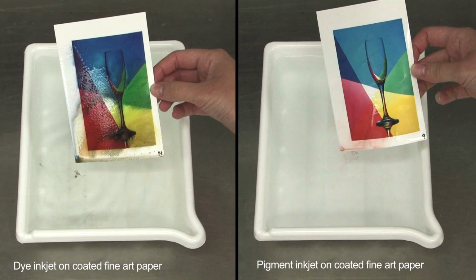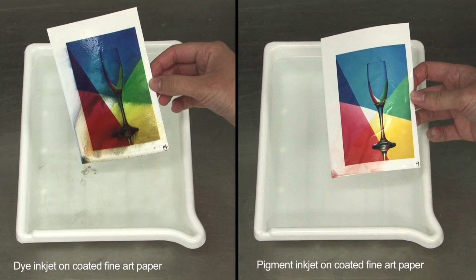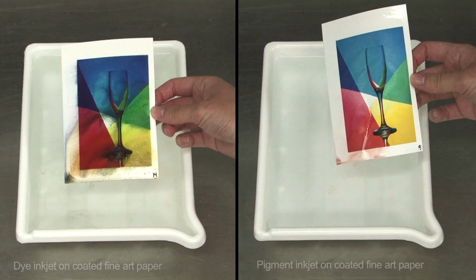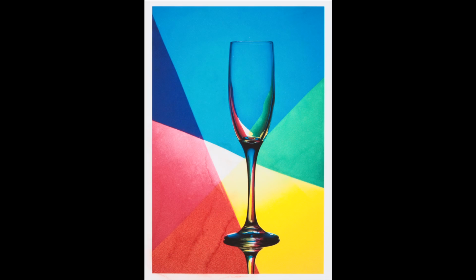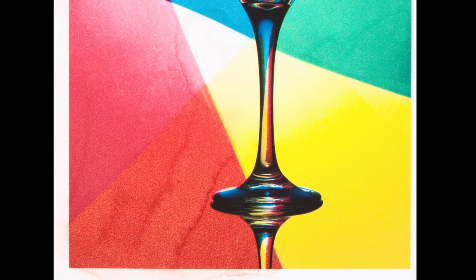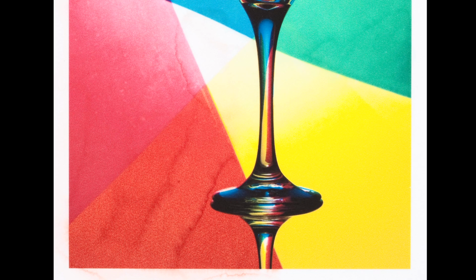Although the sample on the right was printed with pigment ink, the magenta colorant still bled slightly. This is evident by the pink stain in the white border and the tide lines in the red area of the image. This demonstrates that not all pigment inkjet prints are impervious to water damage.